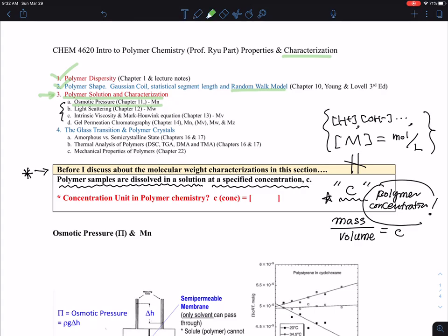Actually, the whole purpose is trying to relate the mass with number of moles. If you're ever able to figure that out, you should be able to calculate different types of average molecular weight. If you focus on counting the number of moles for a given known amount of mass that you can weigh using your scale, you end up calculating Mn. Mn bar is the number average molecular weight. So that's what I'm going to talk about. Always keep in mind, we are using concentration C.